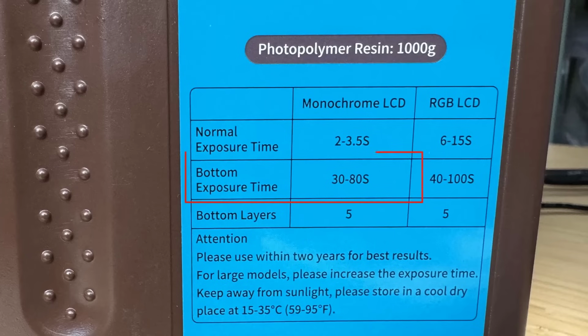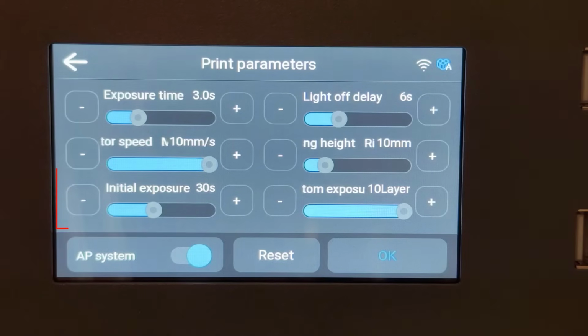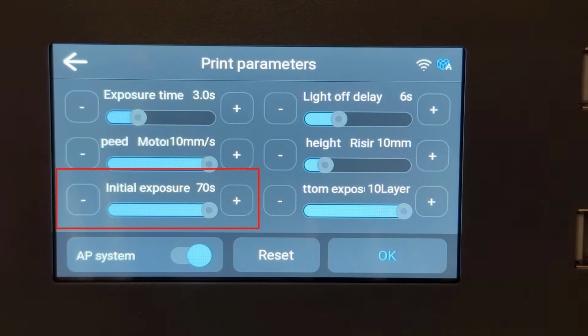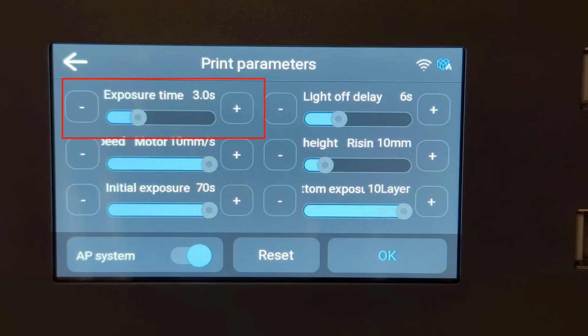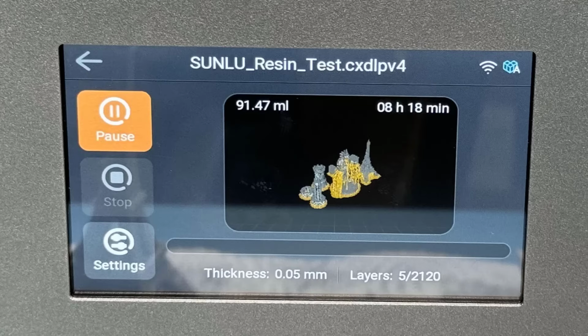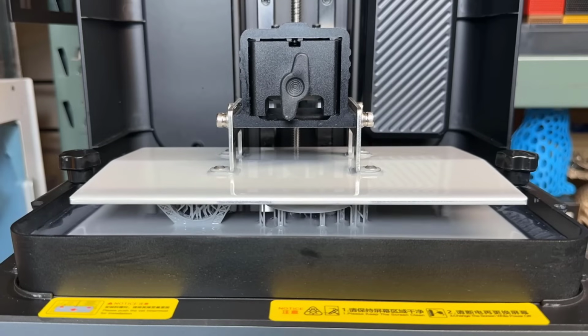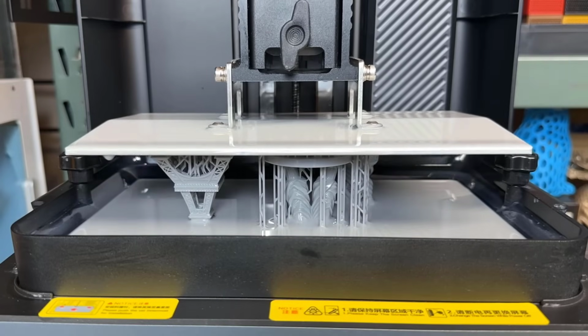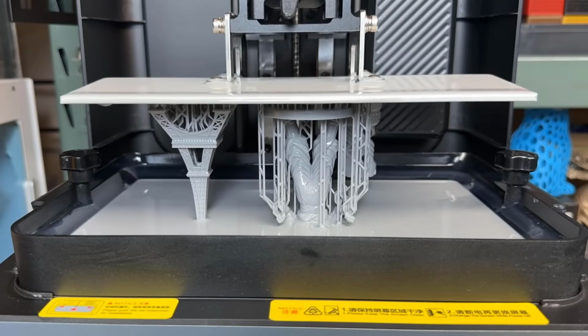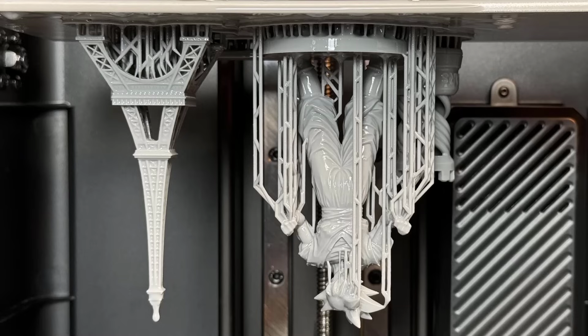Since this resin requires 30 to 80 seconds for the bottom layers, I adjusted the time from 30 to 70 seconds, which is the maximum value I could set on the touchscreen. For regular layers, I also increased the exposure time from 3 to 3.5 seconds. These adjustments increased the total print time by almost 50 minutes, from 7.5 hours to 8 hours and 18 minutes. This time, the print was successful except for the bolt and nut, which were missing. It might be even better to follow the suggested parameters at their maximum values.